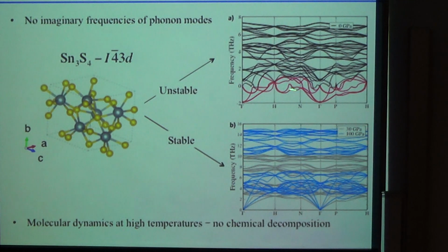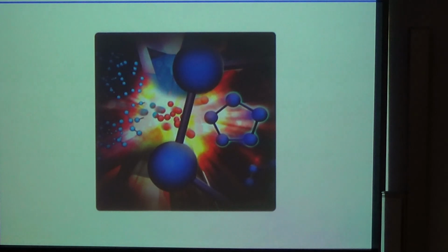And you look at the modes that are imaginary, so they are plotted with negative frequency. If you have a structure with imaginary modes, it means that it's not a local minimum, it wants to slide down somewhere else, right? So in this particular case, at 0 GPa, this new compound that we discovered is unstable at ambient conditions, but when you apply pressure around 30 and 100 GPa, we see that this imaginary phonon mode is gone. Right? So I explained to you how this method works.